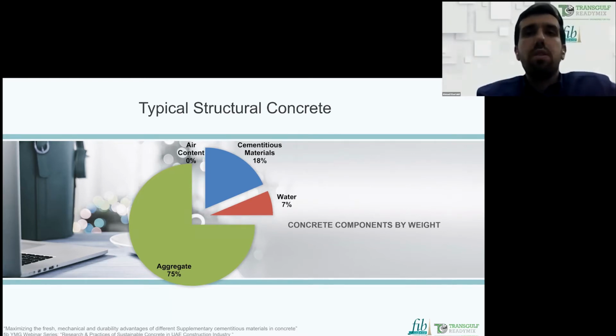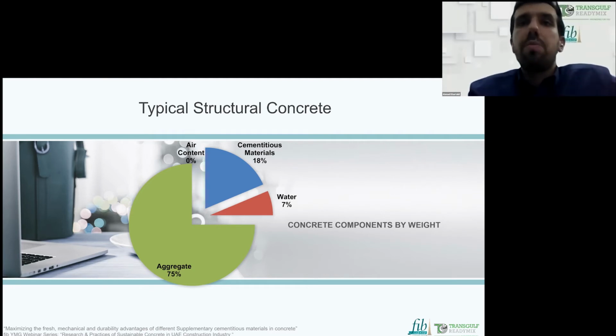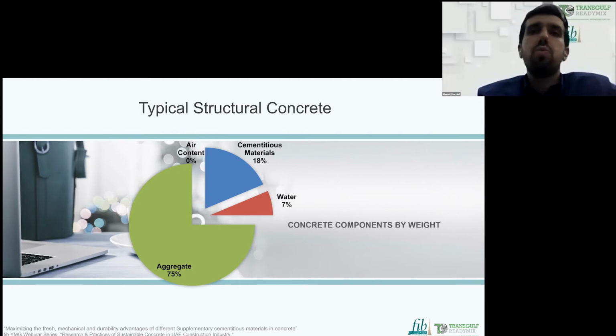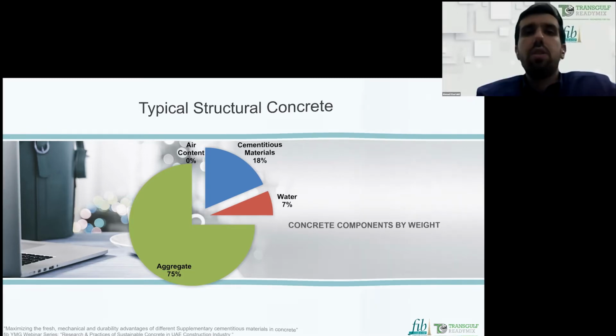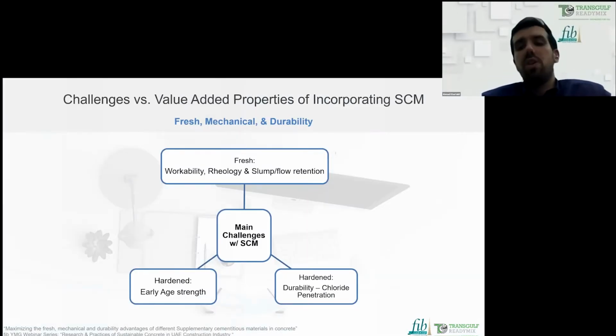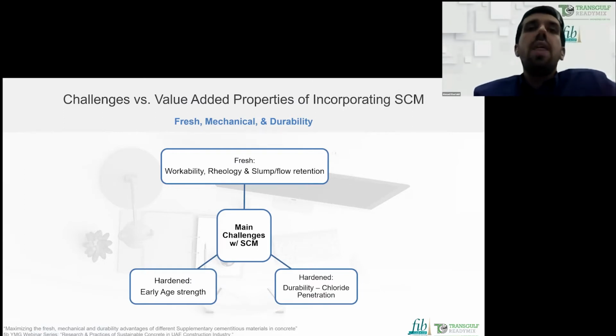As we know, concrete is typically divided by weight into around 75% aggregate, 18% cementitious material, 7% water, and of course there will be air content. Here it's minimal in our region because there is no freezing and thawing. However, now I'll go to the experimental program of this study.